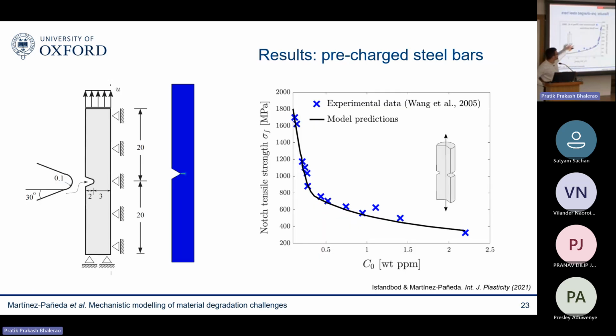So what you see here are pre-charged steel bars. These are high-strength steel bars that were exposed to a hydrogen-containing environment and then tested under uniaxial loading. They had notches. And you can see that the symbols, which are the crosses, fit nicely the model, or the model fits nicely the symbols. These are measurements of notch tensile strength versus hydrogen content. So we are quite happy with the outcome. This is just some representative results of what you can get with these sort of coupled models.